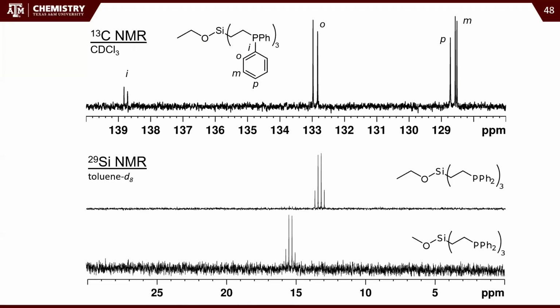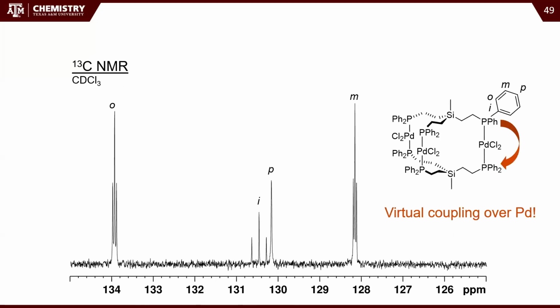Looking at the ligand, we can do silicon and carbon NMR, and you can see some phosphorus splitting. So all of our aryl peaks in the ligand show up as doublets. And then in the silicon, we get a nice quartet because it has J coupling to each of those 3 phosphorus nuclei. We also had carbon NMR of the dimer complex. And this is interesting because we see triplets. So we're actually seeing virtual coupling over the palladium, which is seen sometimes, but it's not so common. It's kind of noteworthy that we're seeing it. So instead of getting a doublet of doublets like you might expect, we just get triplets. Kind of neat.